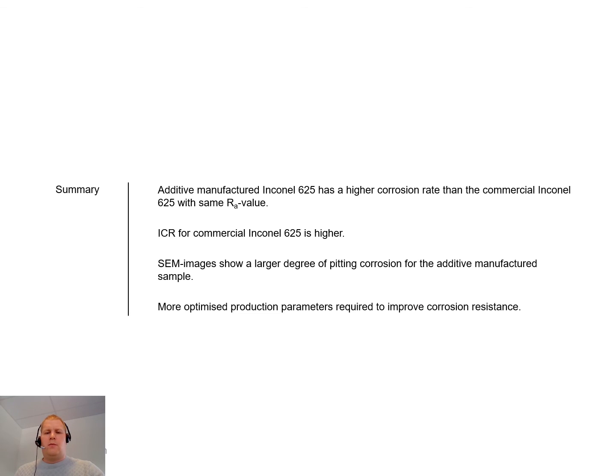So to summarize this work, the additive manufactured Inconel 625 samples have a higher corrosion rate than the commercial ones, despite having the same Ra value. For the ICR it is the opposite: the commercial samples have a higher value compared to the additive manufactured ones. The SEM images show a larger degree of pitting corrosion for the additive manufactured samples. This work clearly shows that more optimized production parameters are required to improve the corrosion resistance of bipolar plates produced with this method.